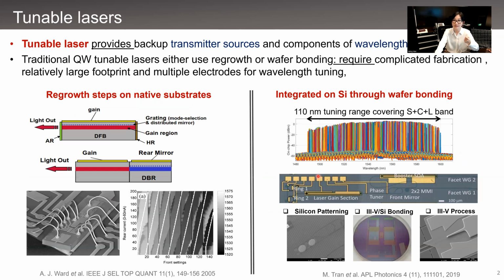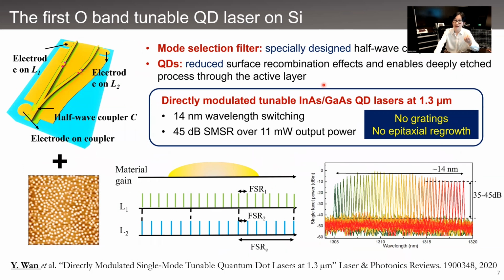In addition to microdisk lasers, widely tunable laser is also a very important branch of lasers that provides backup transmitter sources and components of wavelength routing devices. So the traditional tunable lasers use quantum wells as the active region and are typically fabricated through regrowth steps on native substrate or integrated on silicon through wafer bonding techniques. So these kinds of structures typically require complicated fabrication, a relatively large footprint, and multiple electrodes for wavelength tuning. And here, we use a specially designed half-wave coupler as a mode selection filter, and leverage the quantum dot reduced surface recombination effects to enable deeply etched processes through the active layer.